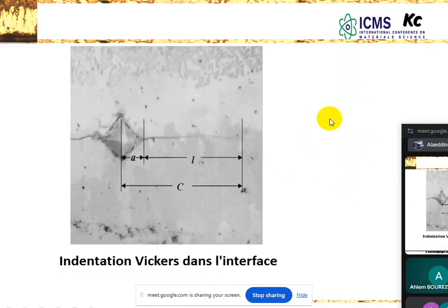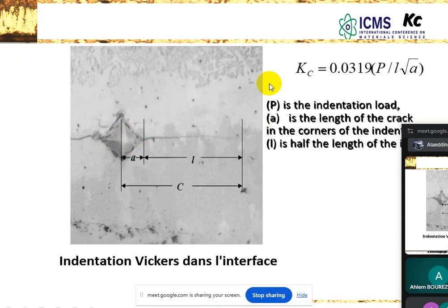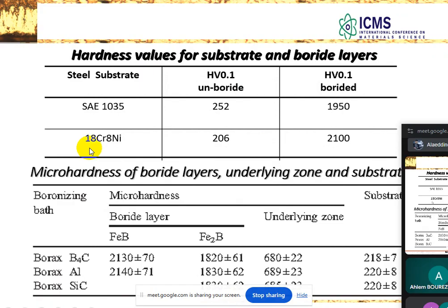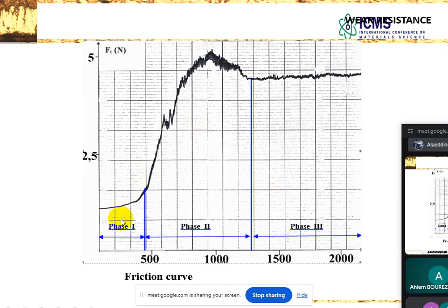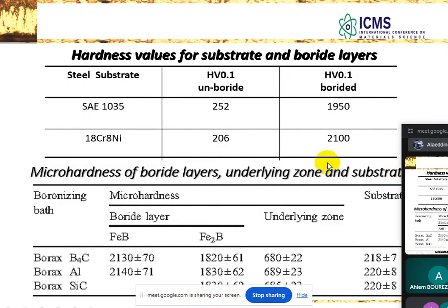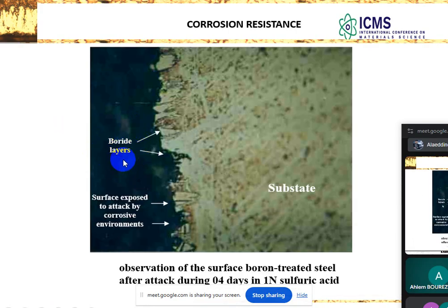And we also measure the thickness and micro hardness of the boride layers with this relation, and we found that it is between 2.82 and 3.75. So for the friction curve, sorry, for the time, this is the first phase, second phase, and the third phase of the friction. And these are our results about iron boride, iron 2 boride, the micro hardness. And then these are the boride layers when we attack with sulfuric acid to study the corrosion.